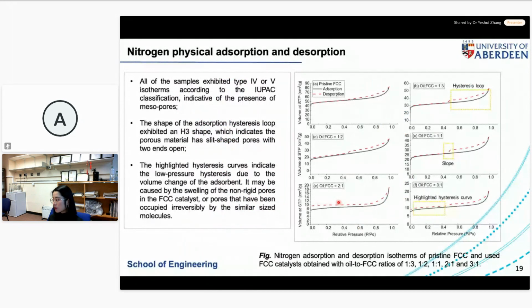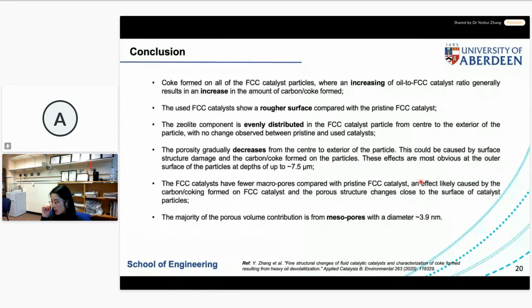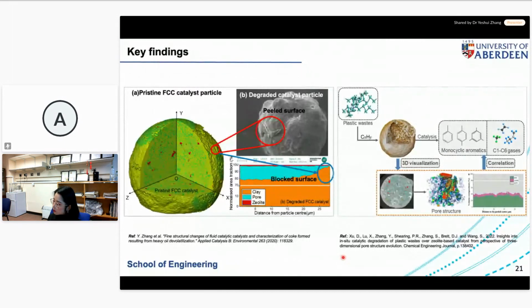Of course, by looking at one catalyst particle, you might ask me how I am going to confirm the results are reliable. Yes, I'm still doing the batch analysis, using a conventional analytical method, to confirm the porosity, pore size, pore size distributions, and pore volumes for the batch of these FCC catalysts. That's the result, so we can confirm our X-ray CT results are rather reliable. I'm not going to repeat this conclusion. If you're interested, there are two publications, so you can look at the details in the references. And those are the graphical abstracts for the two publications.